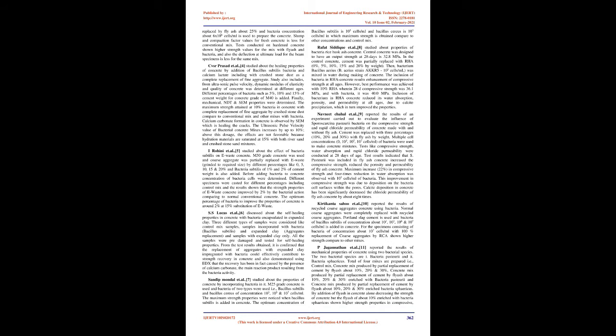S.S. Lucas et al. [6] discussed the self-healing properties in concrete with bacteria encapsulated in expanded clay. Three different types of samples were considered: control mix samples, samples incorporated with bacteria, Bacillus subtilis, and expanded clay aggregates replacement, and samples with expanded clay only. All the samples were pre-damaged and tested for self-healing properties. From the test results obtained, it is confirmed that the replacement of aggregates with expanded clay impregnated with bacteria could effectively contribute to strength recovery in concrete, and it was also demonstrated using EDX that the recovery has in fact been caused by the presence of calcium carbonate, the main reaction product resulting from the bacteria activity.